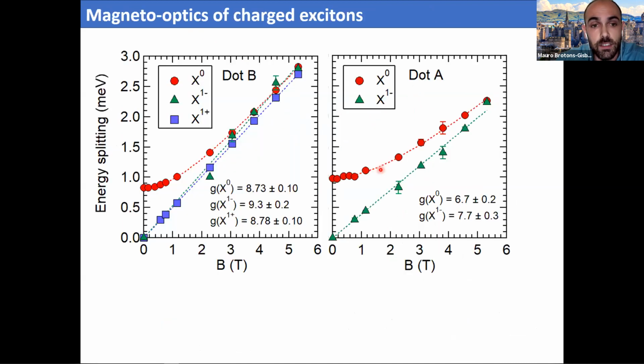And finally, since for the first time we were now able to have both positive and negative trions in our dots, we were able to probe the g-factors of these quantum dots for the first time. We observed that both charged trions have very similar g-factors to the neutral excitons, which had already been reported before, but for the positive trions, this was the first report.